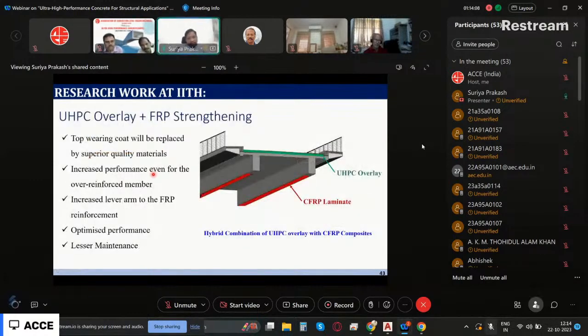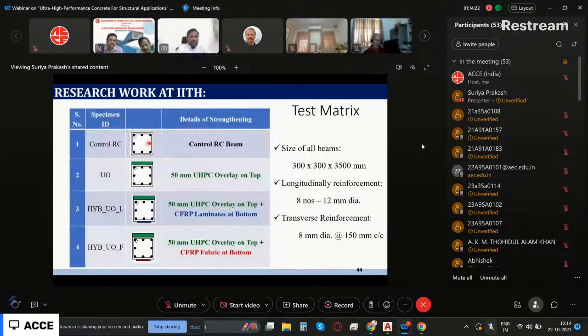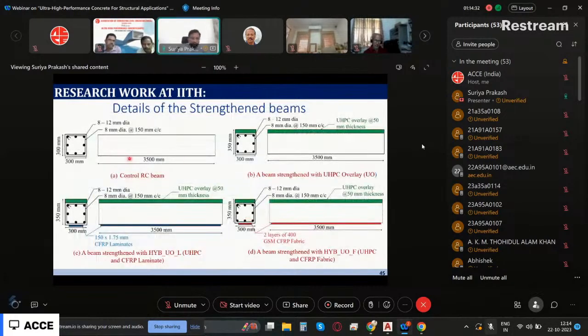And we looked at, okay, for bridges, especially strengthening is an important area. When I combine this UHPC overlay and FRP laminate at the bottom, how is the system going to behave? So that is also, again, we looked at it and we tested several beams, control beams only with overlay, and then we looked at overlay plus FRP. Like that, we played with the different combinations. We found that, and these are some of the details. In fact, I can share the PDF copy of this.